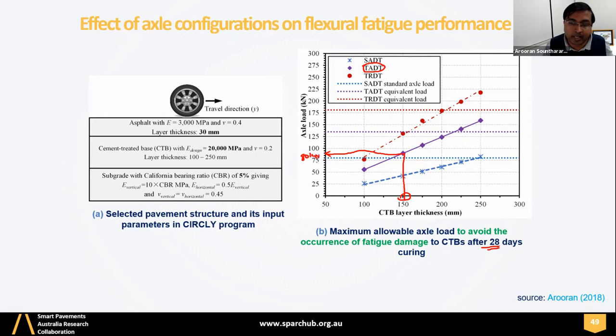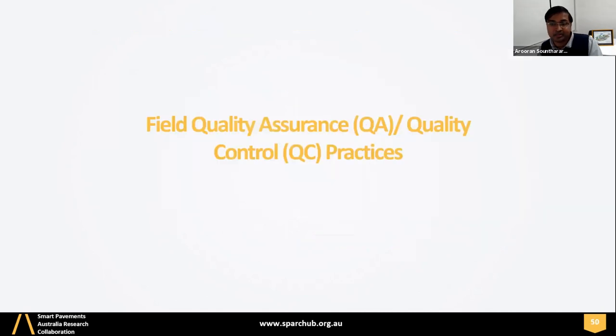That's the maximum, right? So if somebody opens a road after 28-day curing, and if they want to avoid the occurrence of fatigue damage, then they would need at least 150 millimeter layer thickness if they want to allow 80 kilonewton axial load. If they want to allow more axial load, then they need to increase the layers. For example, if they want to allow 150 kilonewton TADT, they would need to increase the base thickness to 250 such that the pavement is not failing. So that's the end of cement treated base construction, testing, and design.